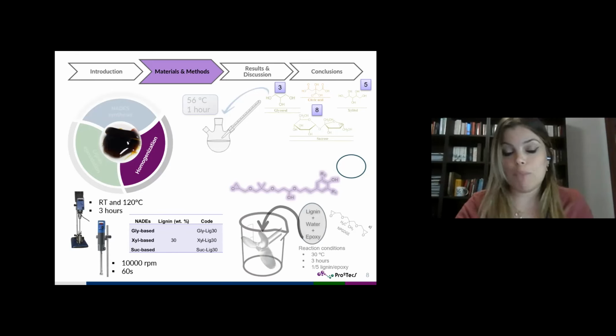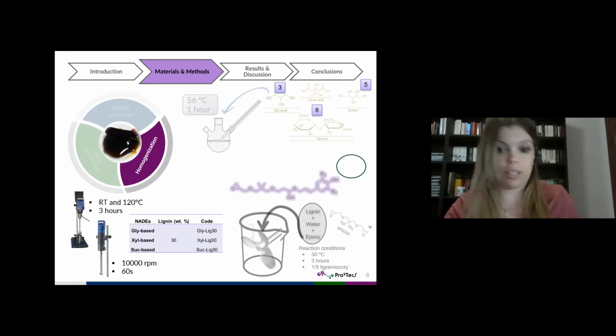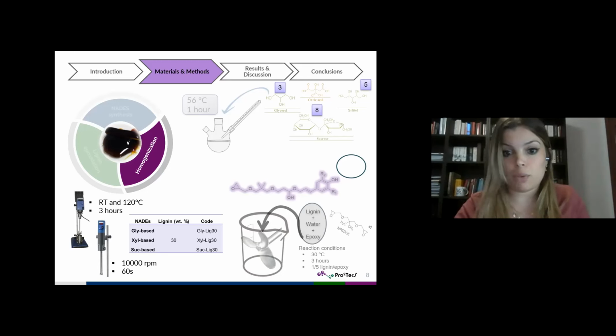this modified lignin and this NADES formulation were mixed in an open vessel, adding 30% of the thickener agent and reacting for 3 hours at room temperature. Finally, the blend, the thickened formulation, was homogenized with a rotor turbine.